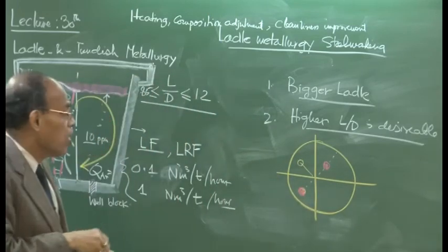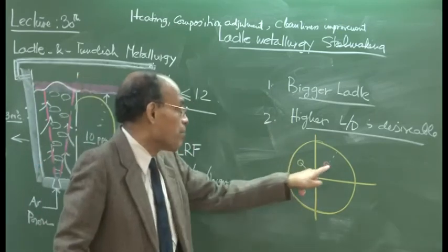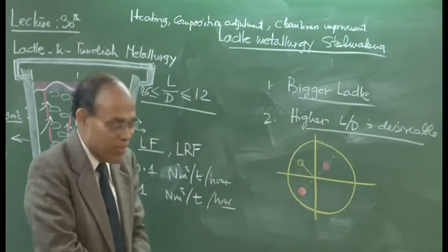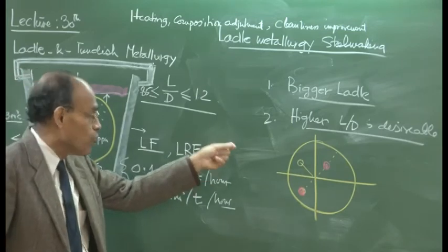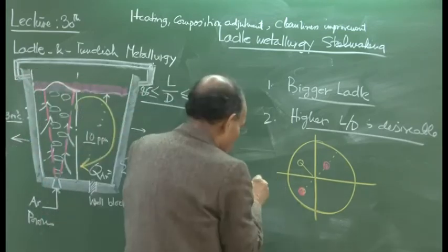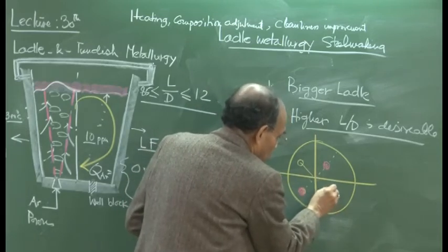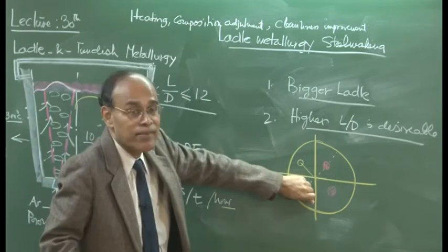And this position of the plug, which is also apparent from the figure, is called the mid bath radius position. If you have two plugs, then you have diametrically opposite plugs. It does not mean that there is a unique arrangement; you can have a plug here also, for example. Some plants use a dual plug where you have this and this plug, not this particular plug.